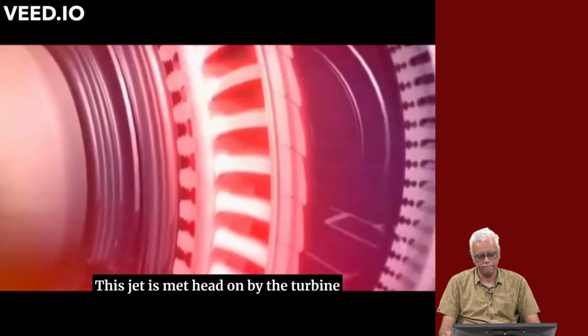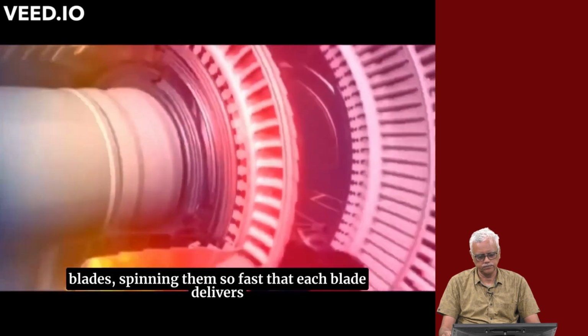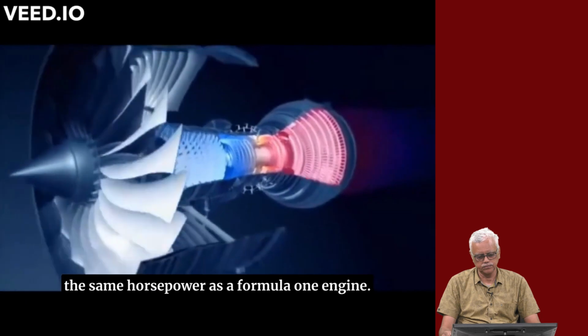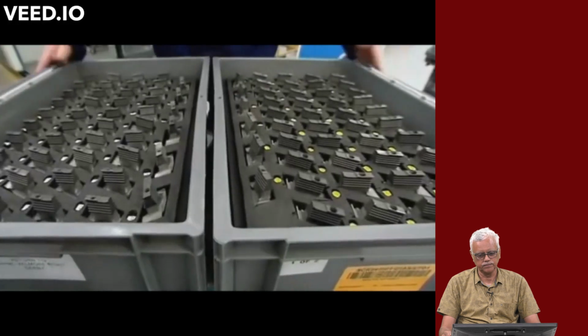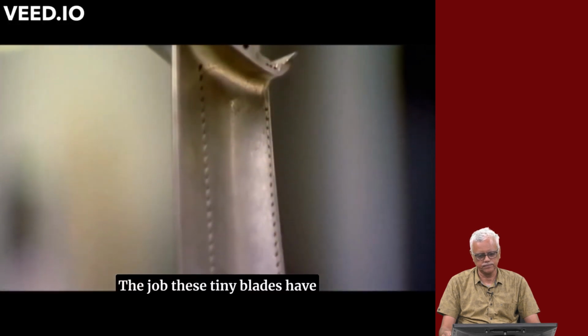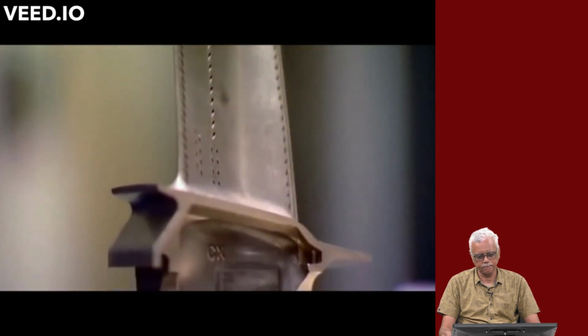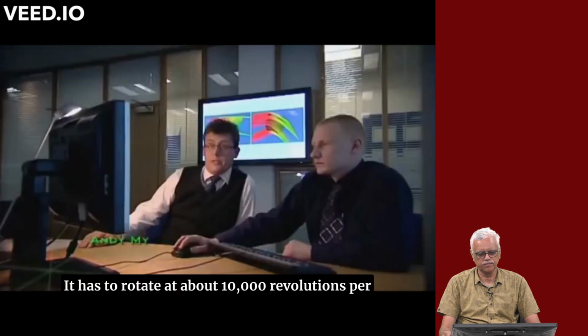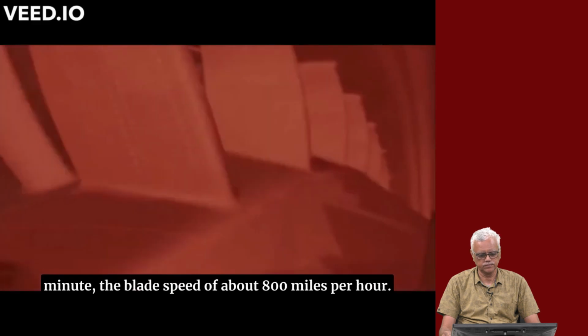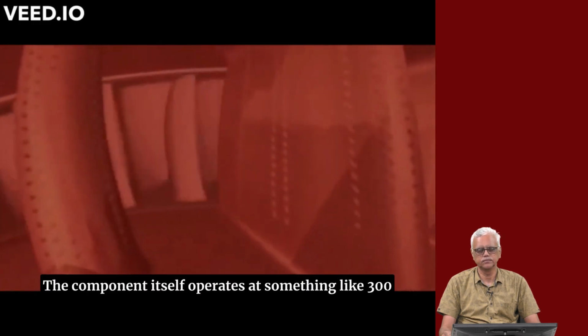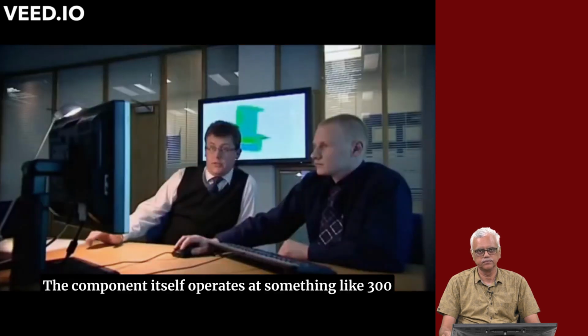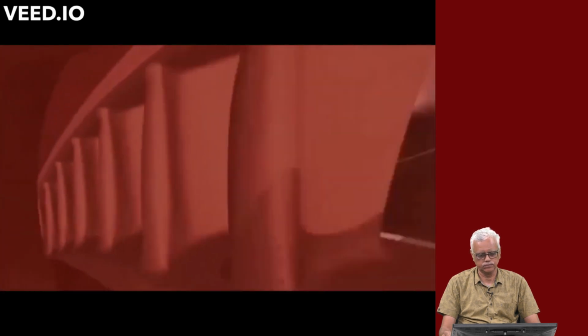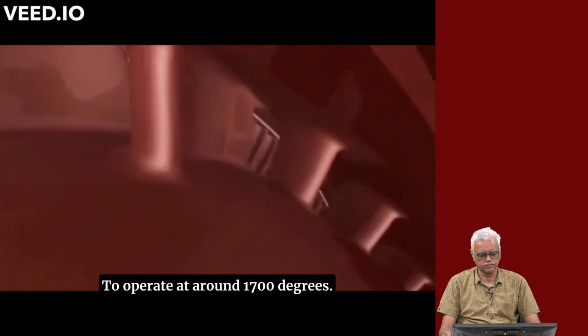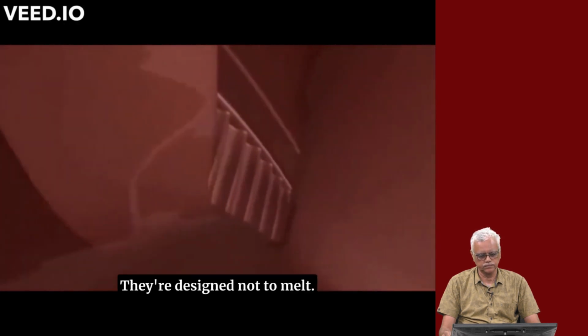This jet is met head-on by the turbine blades, spinning them so fast that each blade delivers the same horsepower as a Formula One engine. The job these tiny blades have to do is unbelievably demanding. The blade exists in a fairly harsh environment. It has to rotate at about 10,000 revolutions per minute, the blade speed of about 800 miles per hour. The component itself operates at something like 300 degrees above the melting point of the alloy. To operate at around 1700 degrees, they're designed not to melt.